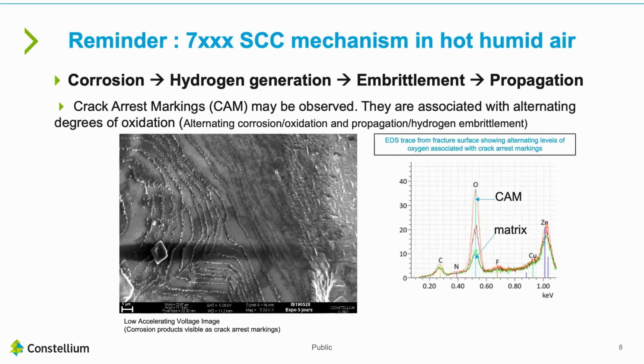In hot humid air, some crack arrest markings may be observed. They are also sometimes observed in the chloride test. So these are the lines here. That's a failure path after rupture of the sample, and these lines correspond to zones containing oxide. It is difficult to see them. You have to be at very low voltage, and you don't have to clean the surface before observation.